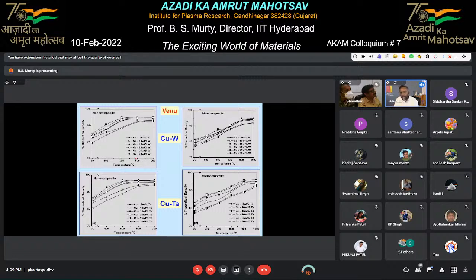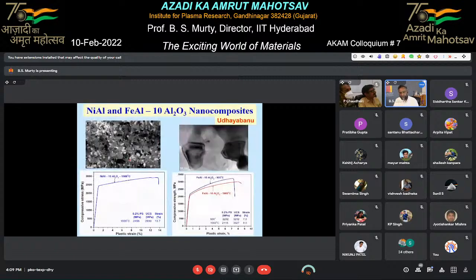A micro composite of copper needs about 800, 900 degrees centigrade to sinter. Here, at 500 degrees itself, you can sinter. We can also make composites, nano composites with intermetallic compounds and oxides as a combination.